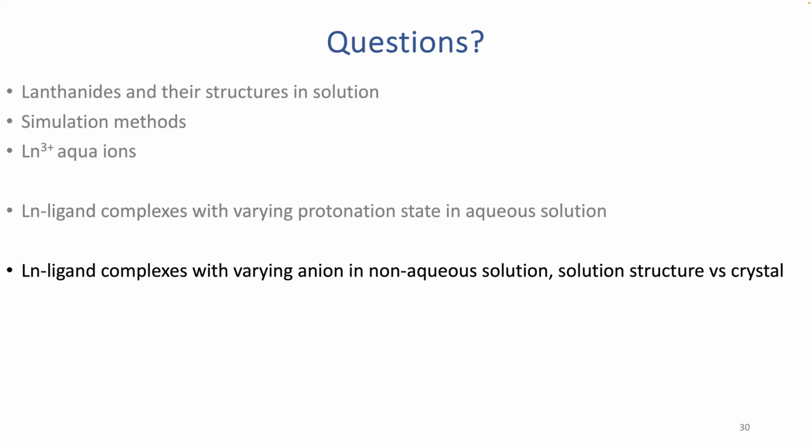Hi. I was just wondering, it seems like your K range in the experimental EXAFS is pretty decent, and there isn't that much noise. You could actually try a traditional EXAFS fit just to see what type of structural parameters you get, and then that would actually guide you in your selection of possible structures from the MD. Yeah.